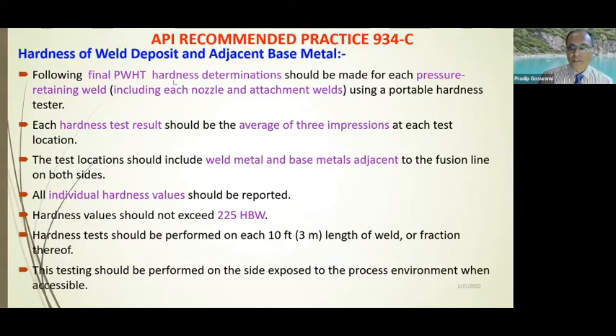Now, following final post-weld heat treatment, hardness measurement shall be done on the pressure retaining welds, including the nozzle and attachment welds. Each hardness test result should be an average of a minimum of 3 impressions on each test location. Those locations include weld metal and base metal adjacent to the fusion line on both sides of the weld. All individual hardness values shall be recorded, and hardness values should not exceed typically 225 HBW. And these tests shall be performed on the side exposed to the process environment when accessible. That means we need to have the hardness testing predominantly done on the internal of the vessel, as well as on the external surfaces also.